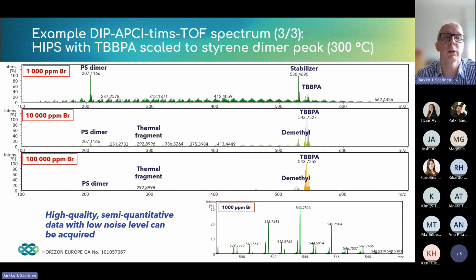So in the case of 1000 ppm bromine content, we see that the PS dimer peak is the most representative peak on the spectrum. And then as we increase the amount of the TBBPA, the relative content of the TBBPA is increased compared to the PS dimer peak, as one would expect. And by doing this relative signal strength, we can also do semi-quantification of the amount of these substances in the sample.